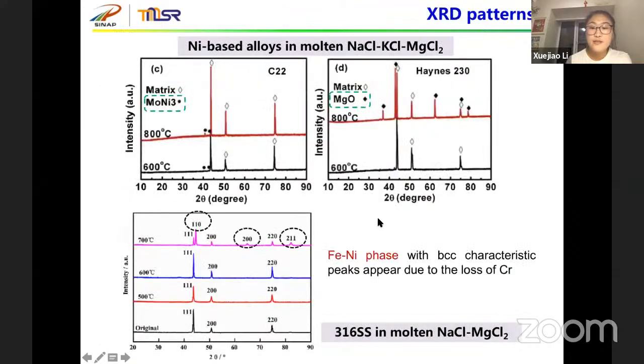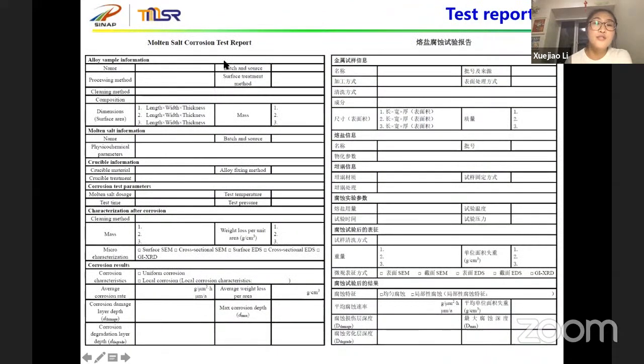In addition, new phases are formed in the alloy matrices, as seen from the XRD patterns. At last, a corrosion test report will be completed, including the alloy sample information, the molten salt information, and the crucible information, as well as the corrosion test parameters and results. Here we have two versions, in English and Chinese, and it's also open to the public.